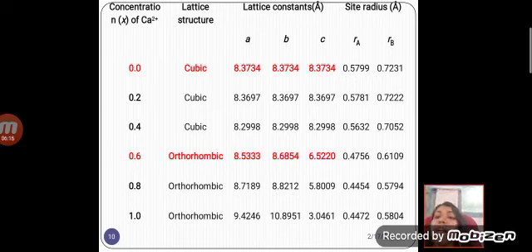We can see that for 0% calcium, the magnesium ferrite sample, the lattice structure is cubic and the lattice constants a equal to b equal to c, which corresponds to a cubic structure. And when it comes to 0.6, that is 60% calcium, the structure shows a transformation to orthorhombic until 100% calcium. And the lattice constants a, b and c values are different, which is typical for orthorhombic structures.